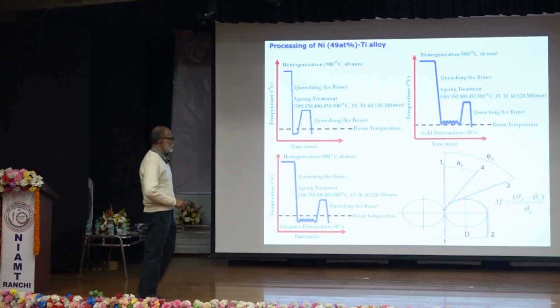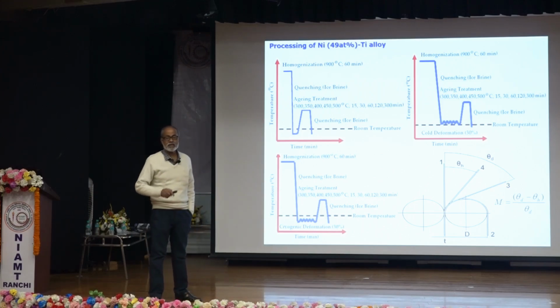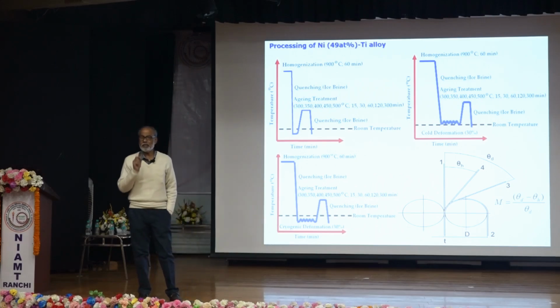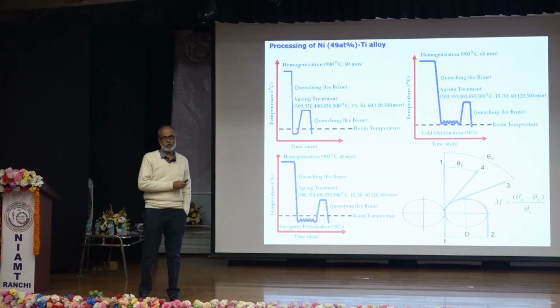And this is how we determine recoverable strain, how the martensite recovery experiment is conducted. This is very simple. We have a roller, and we wound a wire around the roller. Now when we release the load, there will be a spring back. Right? It will go back to some point. And when you heat it, it will recover certain strain. It will go to full. Right? So we assign a recovery ratio, which you can measure actually. You can measure this location and this location. So we call it theta d minus theta h by theta d. That is the measurement of strain recovery by virtue of the martensitic recovery process.